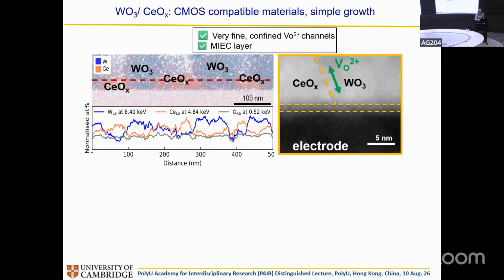And here what we've done is we've made very fine confined oxygen vacancy channels. And where are they? They're at the boundaries between two materials like we had before. So this is a composite, cerium oxide and tungsten oxide. You say, why those materials? Well, they are CMOS compatible. And the cerium oxide is quite a good ionic conductor as well, especially when it's got some vacancies in it. And you have these interfaces again. They're not as nice as the vertical interfaces. Remember, these are simpler systems now. Temperature's a bit lower.